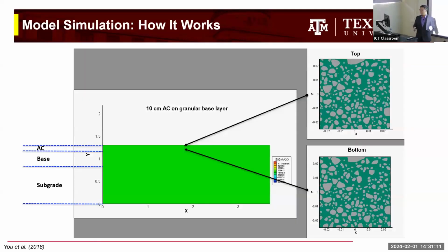So we have to deal with that. Here is a demonstration slide. I have a 3-layer asphalt pavement, AC, base, and subgrade, and we multiscale many elements with a representative volume element. We looked at just two locations for the demo, top and bottom, and we apply truck cycles. I don't know if you can see something going on at the bottom one. Hopefully you can see a lot of small lines develop, like initiation of cracks, like fatigue.